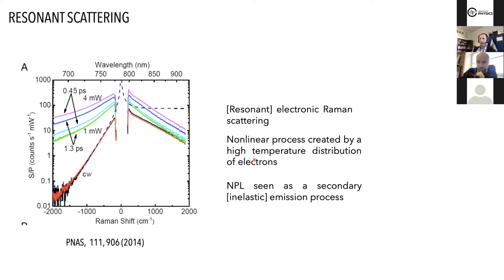And also, we'll be considering a slightly different family of hot electrons, and this is about semantics, but just to set the record straight with what I'm going to be talking about later on, these hot electrons are considered thermalized between each other. So we can assume that the electron distribution follows a Fermi-Dirac distribution. Okay, these are not non-thermal electrons, which will be swiftly produced after the absorption of the pulse.